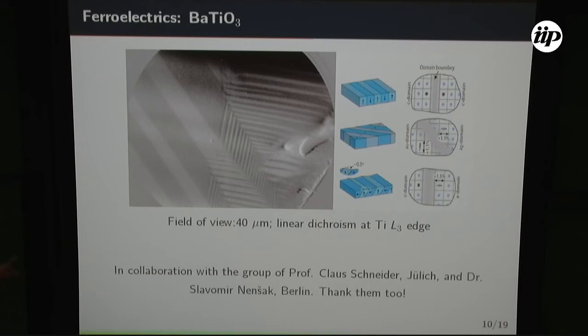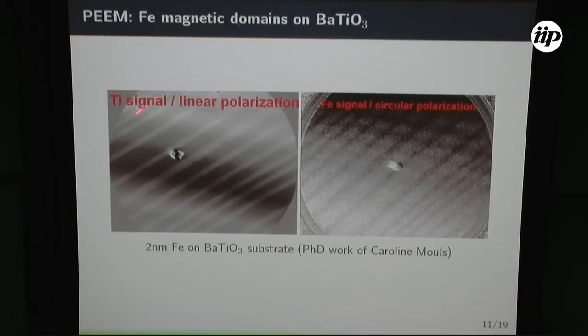What we did then, this is the work of our first PhD student, Caroline Mouls. What she did, she evaporated on the top of this barium titanate monocrystal a thin wedge of iron, simply iron, going up to 5 nanometers, more or less. If you measure the magnetic domains of iron, at the iron edge, for the thick layer you see the standard domains for a thin iron layer in the plane, randomly distributed. But when you measure in thicknesses smaller than 2 nanometers, you see an alignment of the magnetic domains